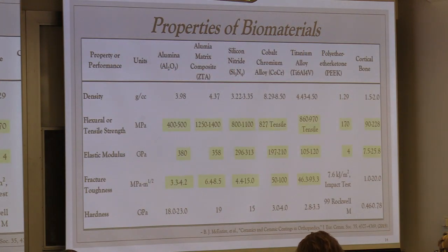Okay, so let's talk a little bit about the properties of biomaterials here, just to kind of contrast them and accentuate a little bit about the differences and what's going on with silicon nitride. And I've highlighted here 3 particular areas: flexural strength, or strength itself, elastic modulus, and fracture toughness values. And I've just shown 3 particular ceramic materials: alumina, aluminum matrix composite, which is also known as zirconia toughened alumina, and silicon nitride. 2 metal components which are in common use: cobalt chrome and titanium. A plastic, which in this case I highlighted was PEEK, polyether ether ketone.